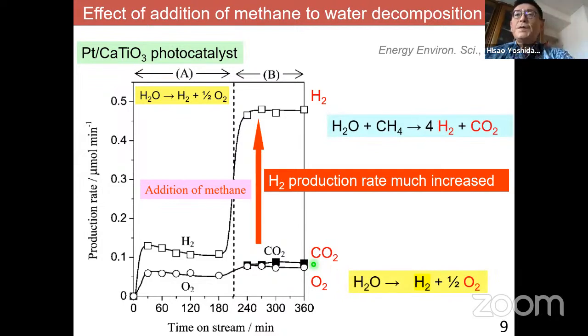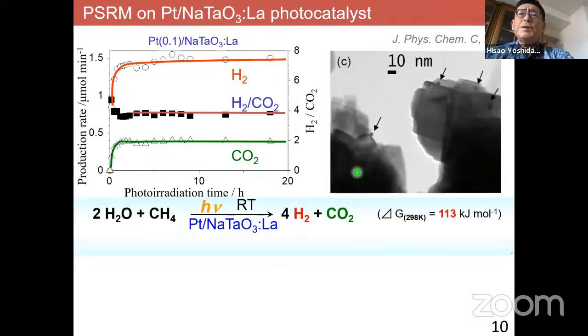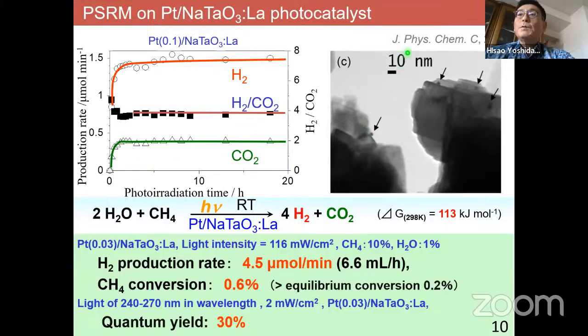So in this reactor, the methane steam reforming is promoted to produce hydrogen, and also water splitting occurs. Now we are concentrating on the methane reforming. Here we developed some catalysts, and this is one of the most active ones. The catalyst is sodium tantalate with lanthanum doping, and we load the platinum co-catalyst on it, and the reaction occurs very stably. This is the production rate of the hydrogen and the carbon dioxide. It continuously produces the hydrogen and carbon dioxide in this reaction scheme. So that is our first success to promote this one.